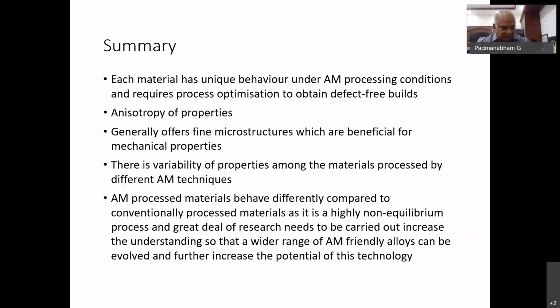And to summarize, each material has unique behavior under AM processing conditions and requires process optimization to obtain defect-free builds. We have to tackle the anisotropy of properties. It generally offers fine microstructures which are beneficial in terms of mechanical behavior. There is variability of properties among the materials processed by different techniques. And then AM processed materials behave differently compared to conventionally processed materials, as it is a highly non-equilibrium process.